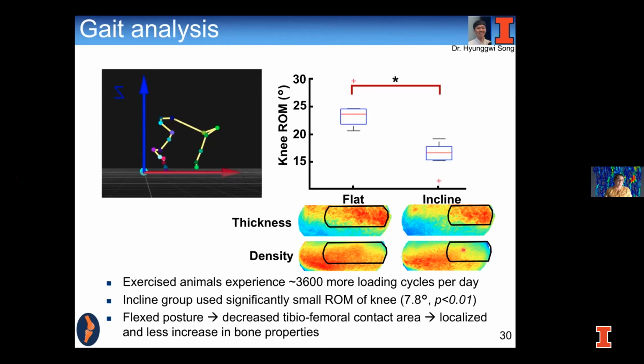And it might be because the bone is still undergoing mineralization. So if it's induced a response where the bone is now trying to adapt, it might be that we are still in the middle of a full remodeling cycle, in which case adaptation would occur by an initial laying down of undermineralized bone that would eventually mineralize over time. We're looking at some fluorochrome data to actually see what the modeling and remodeling rates are, but we don't have any of those results at this time.